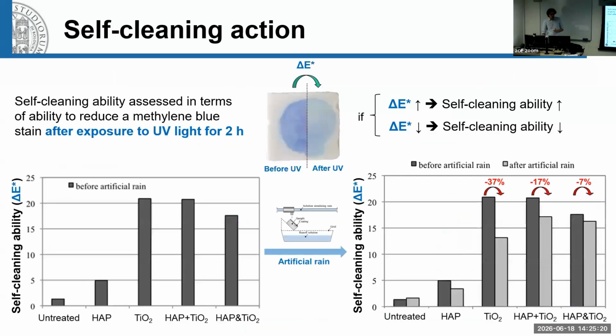self-cleaning ability. What we found was indeed that these coatings have a self-cleaning ability. You see here the idea. So usually these tests are done by having a substrate, in this case it was marble. We put a stain of methylene blue, a certain chemical that forms a blue stain here. And then when the surface is functionalized to be self-cleaning, after exposure to UV light, the stain fades away. So you obtain this kind of self-cleaning ability. The variation in color in doing this is a measure of the self-cleaning ability.